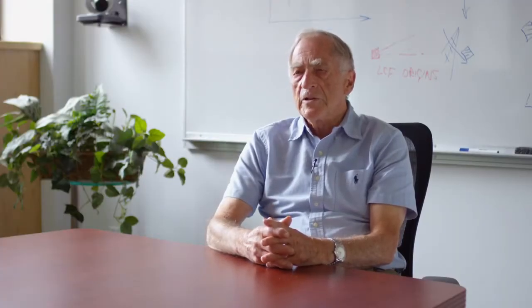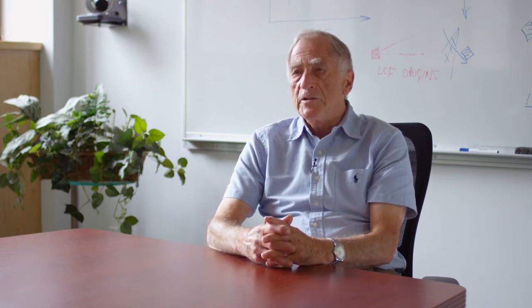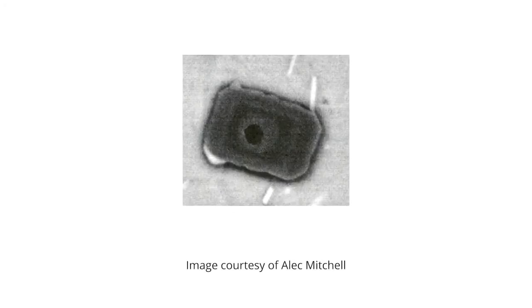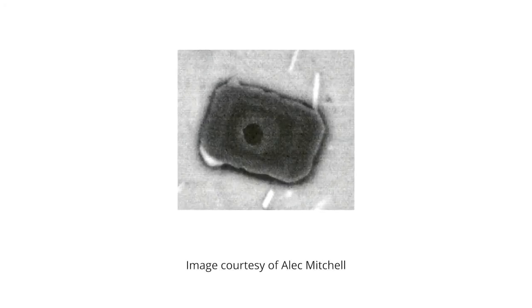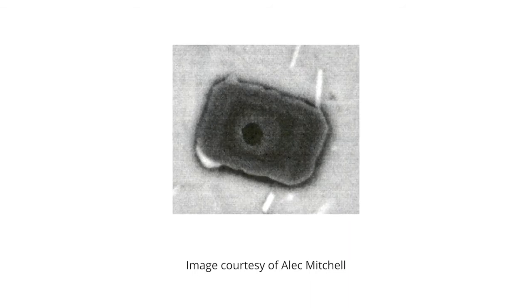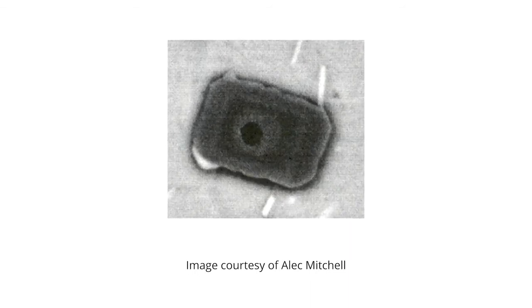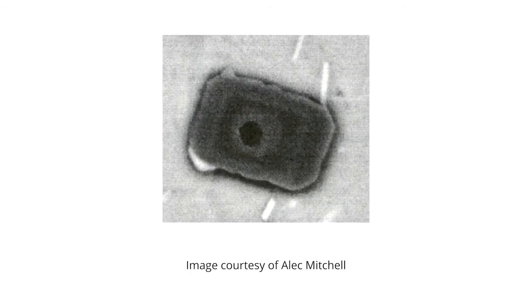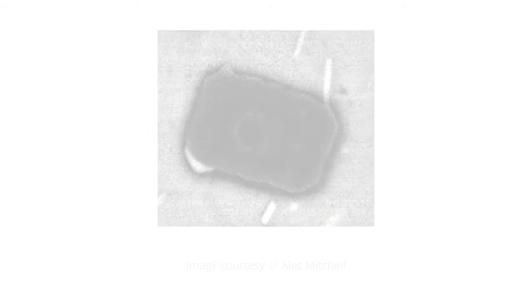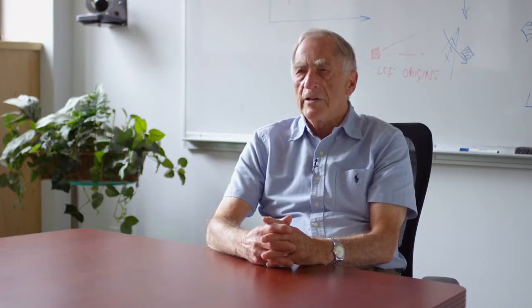So our conclusion was that titanium nitrides were an important part in determining the behavior with respect to the oxide inclusions. The second factor that we found was that the primary carbides in 718, the niobium carbides, nucleate on titanium nitrides during their formation. That's why the industry calls them carbonitrides. They are in fact a composite particle. And we found that the larger titanium nitrides were nucleating the carbides, which caused all the problems with low cycle fatigue. So we concluded that on the basis of that, if we got rid of the titanium nitrides, then those problems ought to be greatly eased.